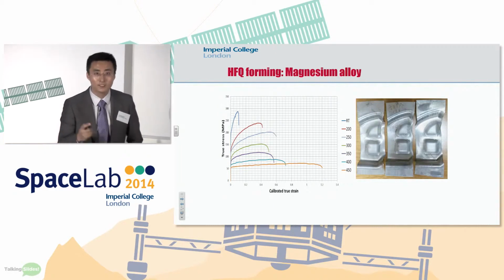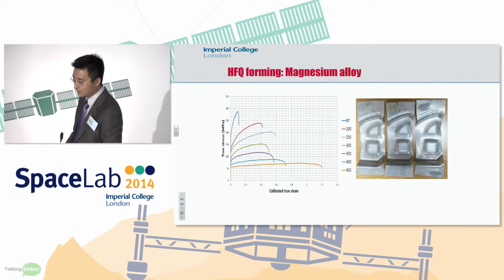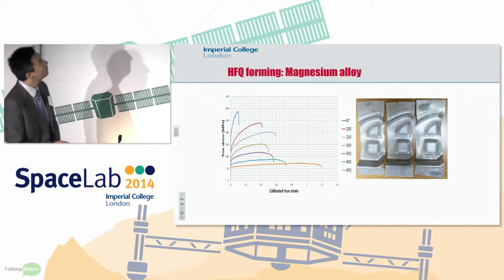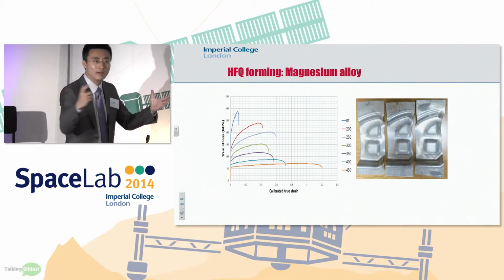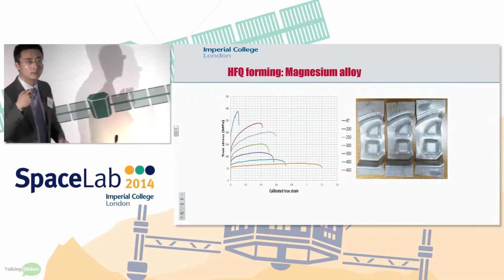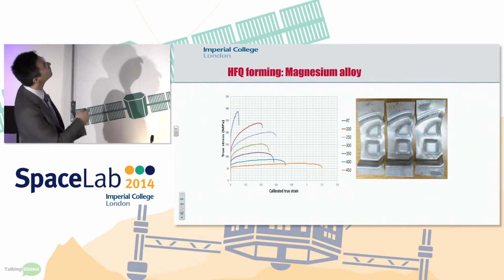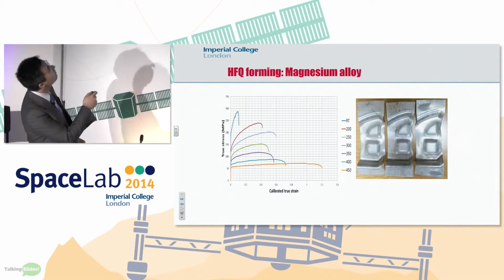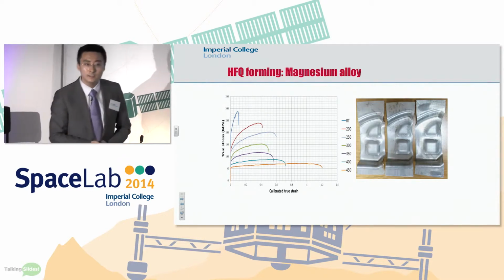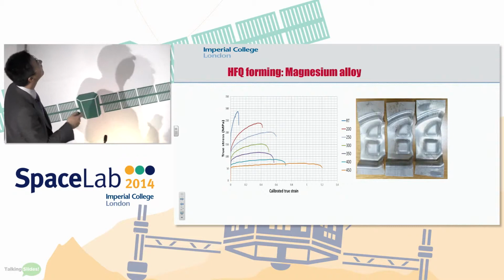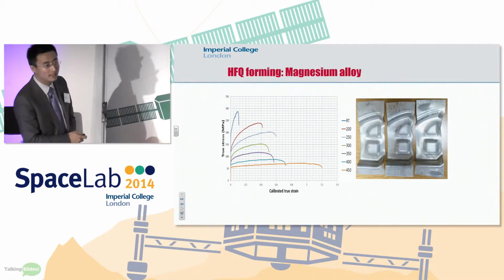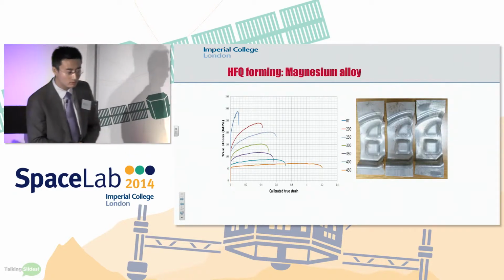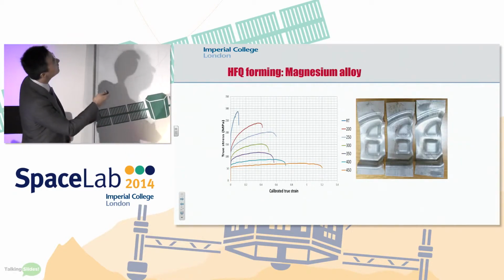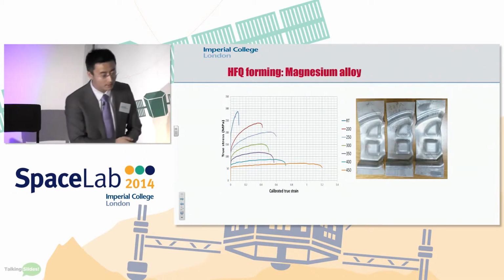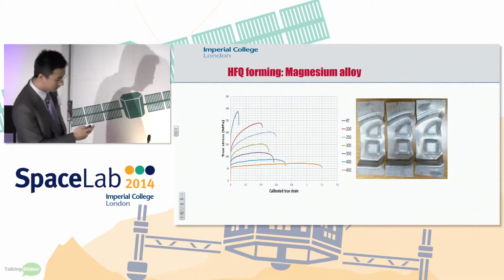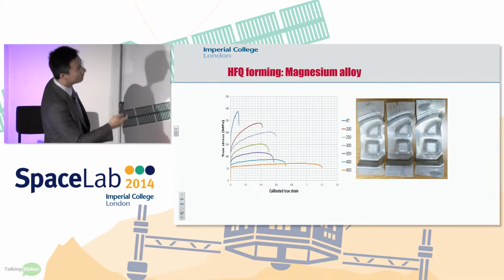At Imperial, we have the latest model of Gleeble, which is the most advanced material tester in the world. So we can simulate the complicated temperature evolution during the deformation process. Of course, we can simulate or reproduce the HFQ temperature evolution. We can see that, especially at room temperature, the ductility of the material is very, very poor. So it's not possible to form any shape by cold forming or traditional metal forming technologies. But if we look at this curve, which is the HFQ forming condition, the ductility has increased significantly. So we use this forming condition to form the part very successfully.